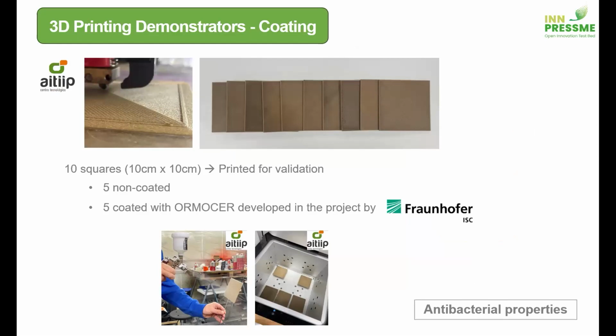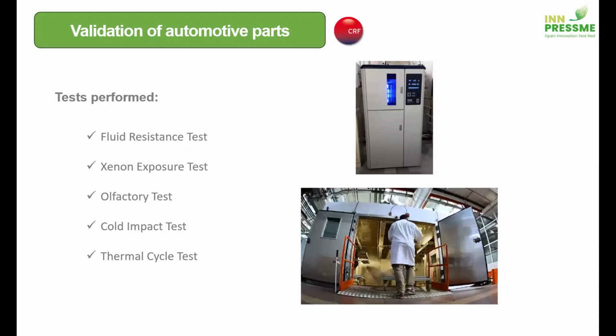What we did in terms of validation, while we were getting the best parameters for the 3D printing, was to use 3D printed squares of 10 by 10 centimeters, which were printed just for validation purposes. We coated 5 of them with the Ormocer developed by Fraunhofer, which, as I mentioned before, provides antibacterial properties. These 10 plates, 5 coated and 5 non-coated, were sent to CRF for validation.